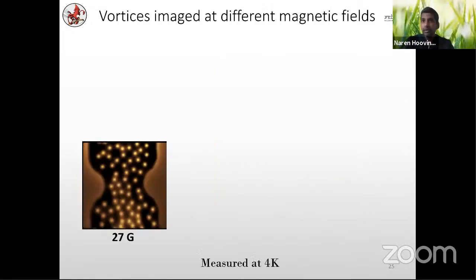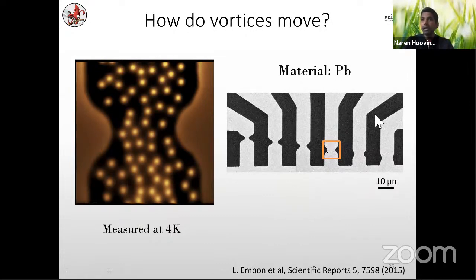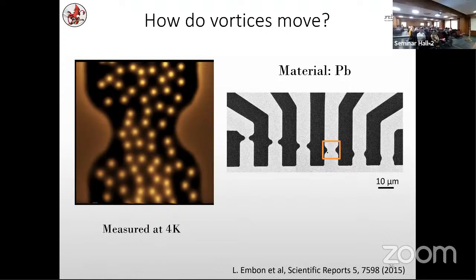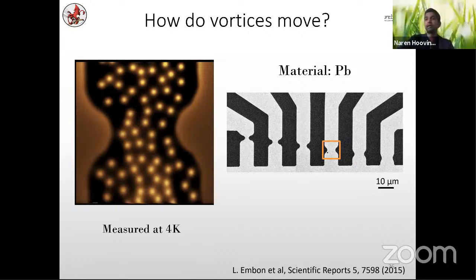Yeah, sure. So when these films are deposited, typically there are imperfections in the film, and there are certain regions which have maybe weaker superconductivity, which have crystal defects. They don't form as a single crystal, but there are defects in the single crystal. And these regions are energetically more favorable for a vortex to sit at. So these regions are basically called pinning centers of the vortices. And of course, they're dependent on the material. They're also dependent on how the material is deposited.